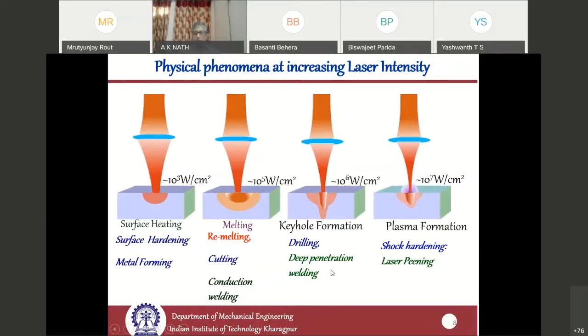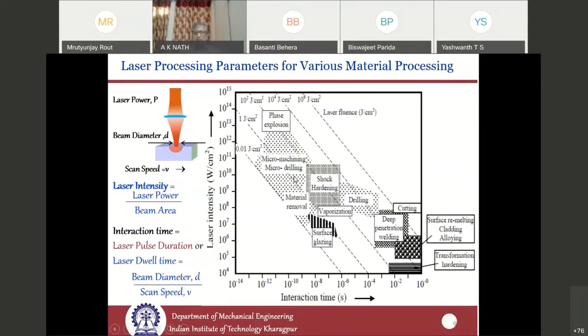So by controlling the laser power density on one axis and the laser interaction time on the other axis, ranging from seconds at the right side to 10 to the power minus 14 second, you can realize all these processing applications like transformation hardening, forming, cladding, alloying, cutting, welding, drilling, shock peening, phase explosion, and micro machining.